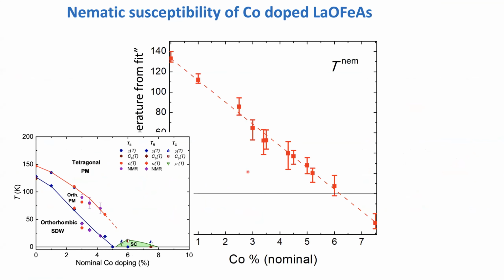Yeah, sure. In the parent phase, you observe T nematic about 20 or 30 Kelvin below the actual structural transition, right? But it looks like from this phase diagram that they are about the same temperature when they reach the quantum critical point. That's right, that's correct. Here 130 degrees is T_nematic, the structural phase transition is 150 degrees. But if you go to this T_nematic at higher doping, it enters the zero.